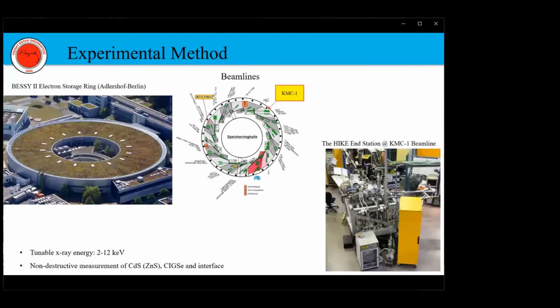High energy X-rays can be obtained in synchrotrons. The HAXPES measurements in this work were performed at the BESSY II electron storage ring located in Berlin. In BESSY II, there are several beamlines available for various purposes. We performed our measurements at the HIKE end station, which is located at the KMC-1 beamline. The advantage of using this end station is that we can tune the X-ray energy between 2 and 12 kiloelectron volts. This provides us a non-destructive investigation of the corresponding interfaces.